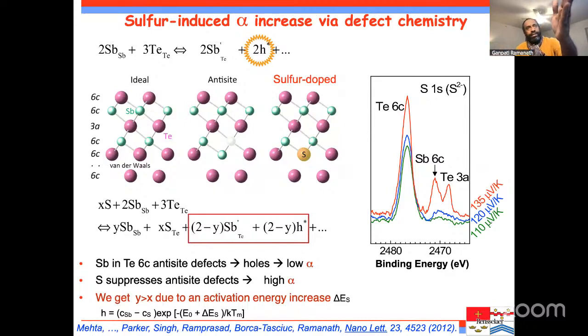So in the ideal material, tellurium sits in tellurium sites, antimony sits in antimony sites. But in real life, thankfully, there are defects, so there can be anti-site occupancy. Now, anti-site occupancy is bad because it can create more charge carriers and decrease the alpha. When you put in the sulfur, it suppresses it.